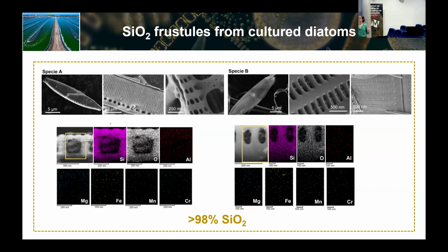And then we have species B. In species B, the pore structure is more complex because we have, for example, pores inside the pores. In both cases, the composition of the material was quite pure. It was mostly pure silica. And even if you have some impurities, you can control these impurities by controlling the media where diatoms grow. So you can have actually always the same impurity. And if you want to change one impurity by another, you can do so. So we are more like in reproducible conditions in here.